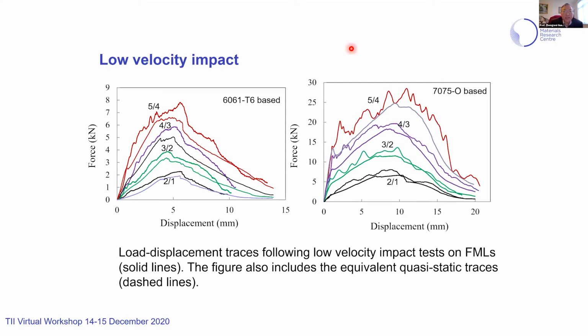This is 7075-based fiber metal laminates, again from 2.1 to 5.4. You can see that with different aluminium alloys, we have quite different impact resistance. With 7075, we get close to 30 kilonewtons peak load, but with 6061-T6 we get about 8 kilonewtons. So you can choose different alloys, and you can even mix them up. You can use some layers of titanium, some layers of aluminium, and the composite. That's the beauty of fiber metal laminates: very flexible stacking sequences.